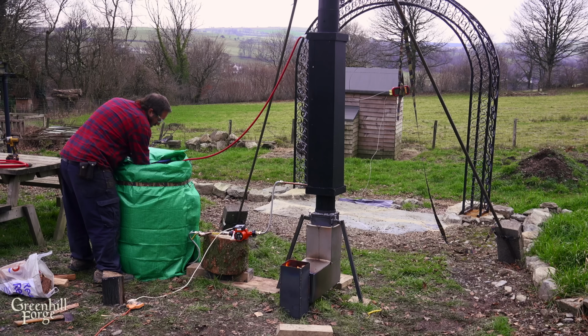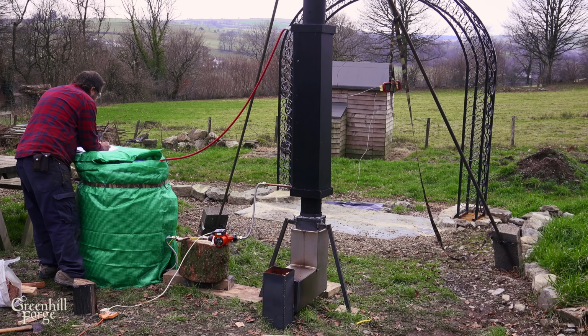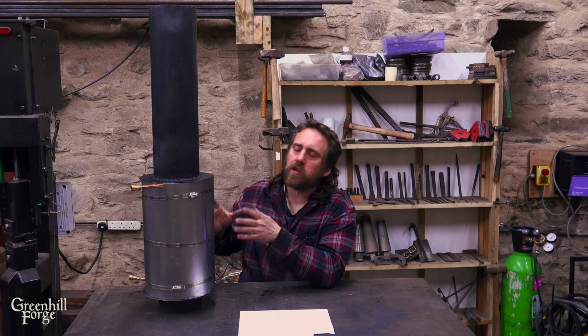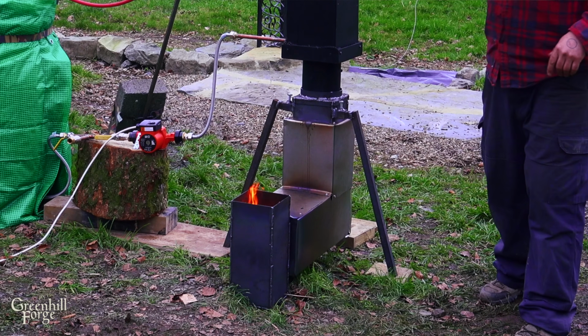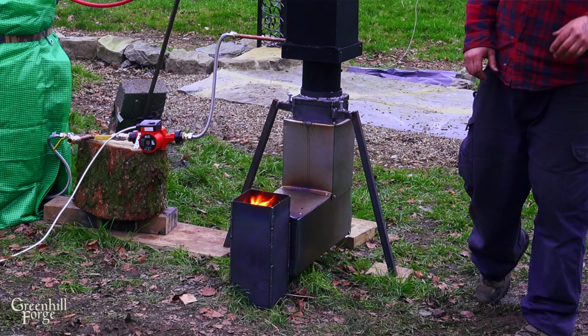But it also comes with a lot of drawbacks, having the coil inside the flue. It's gonna condense a lot more creosote, which is a safety hazard for fires. It's gonna reduce efficiency over time as it builds up and cakes on the coil itself. And it's also acidic, which is gonna have long-term consequences on the metal on the inside. And with increased heat, there's a much greater likelihood of an overheating or an overpressure event. Also, any obstructions within the flue would almost never pass regs for a domestic setting.